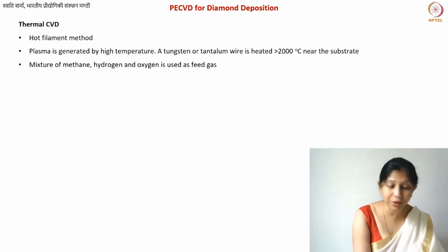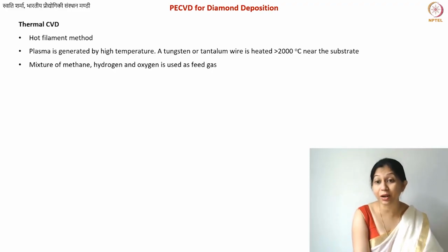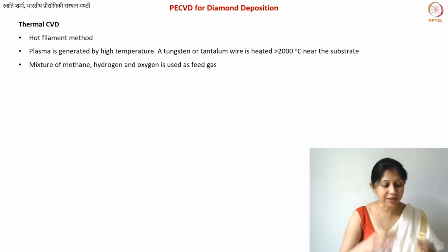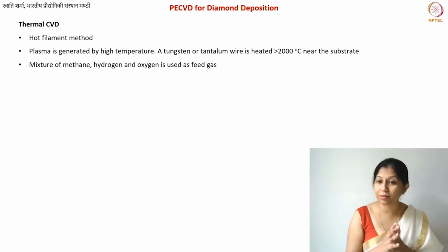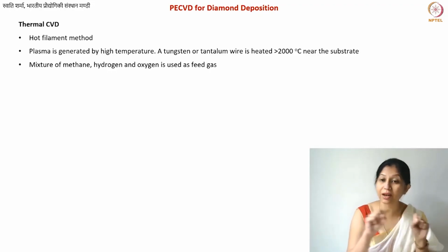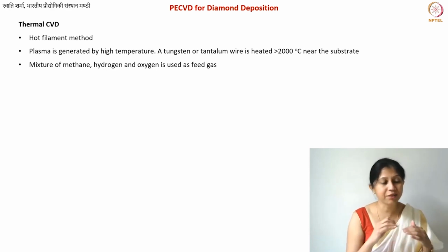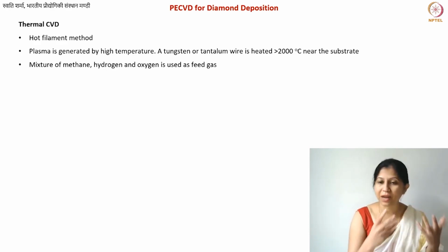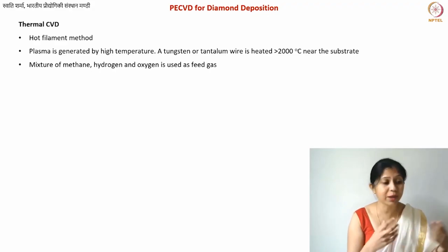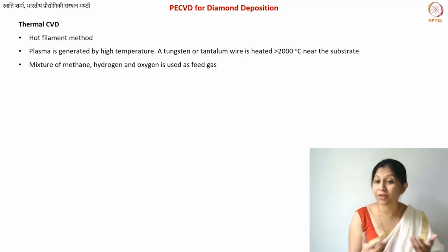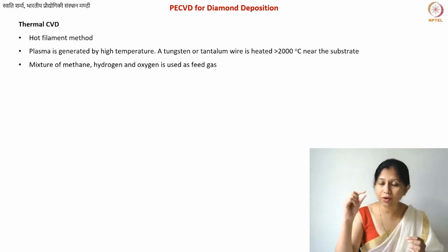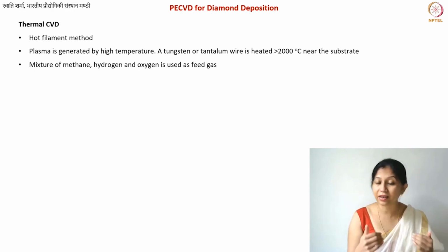One important thing is that this should take place very close to your substrate, because otherwise there will be a very strong temperature gradient. Your wire is heated and you have plasma very close to the wire. But if your substrate is too far, by that time your plasma concentration will drastically decrease, also because of the very strong thermal gradient. So typically you'll have less than 1 centimeter distance between your substrate and the heated filament.